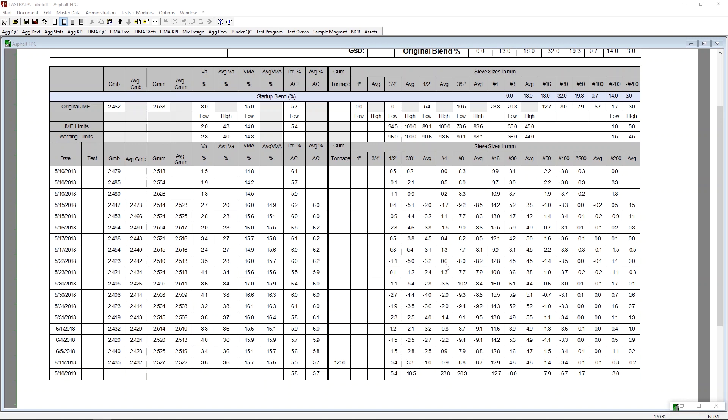So how do we use that in production? What we need to do is look at the product that provides number 8, and hopefully there's a second product that provides number 30. And if that's the case, what we can do then is we can increase the amount of material that is providing the number 8 to get this number up, and we can decrease the amount of material that's providing number 30, essentially making room for the material that we're going to lose.